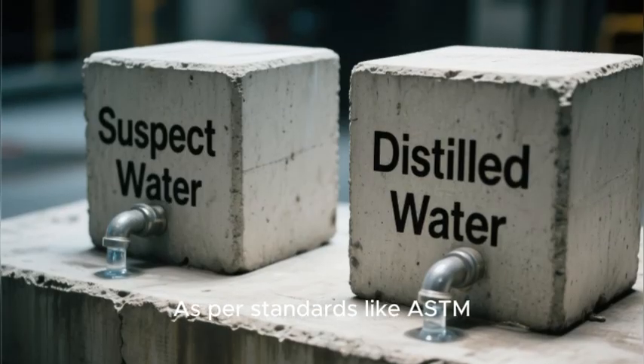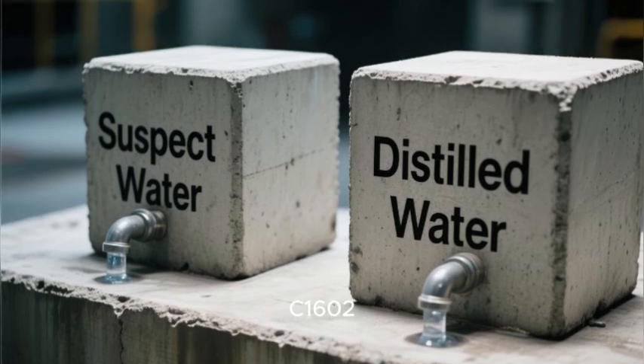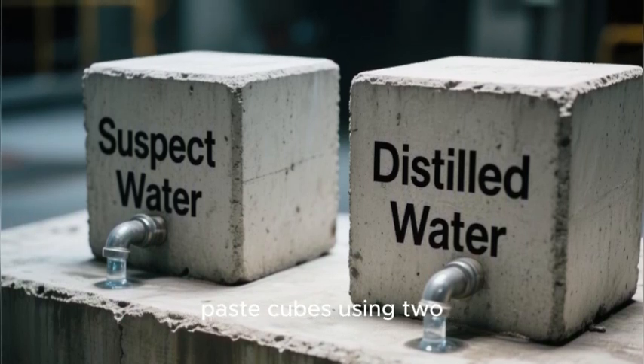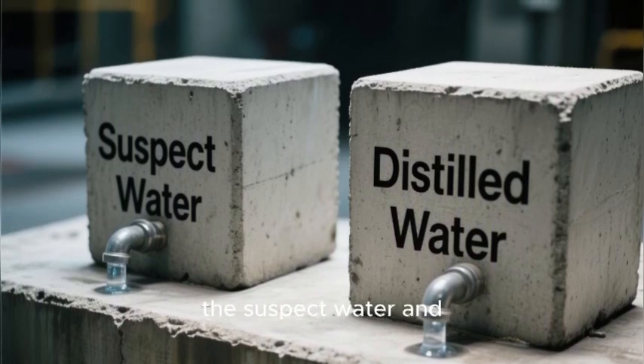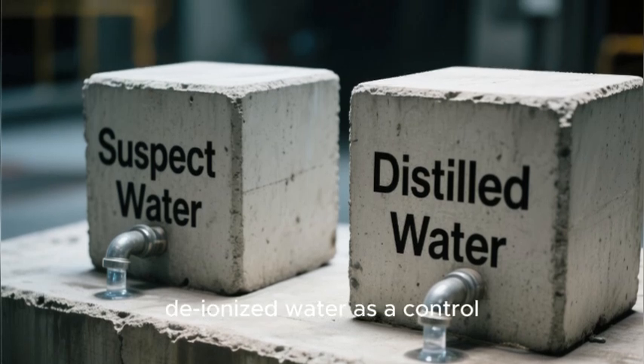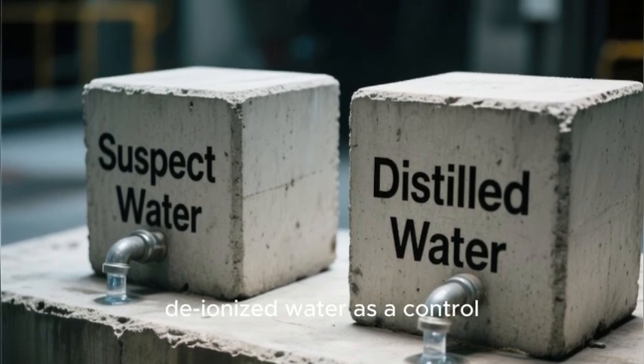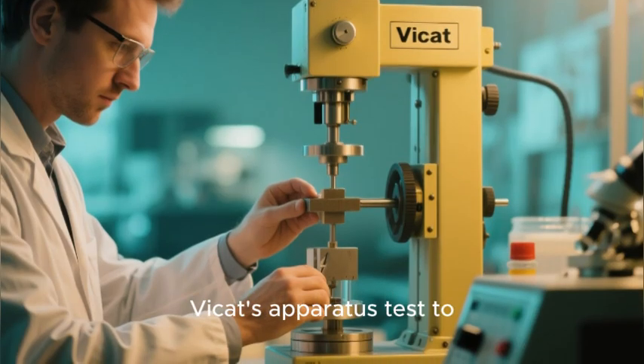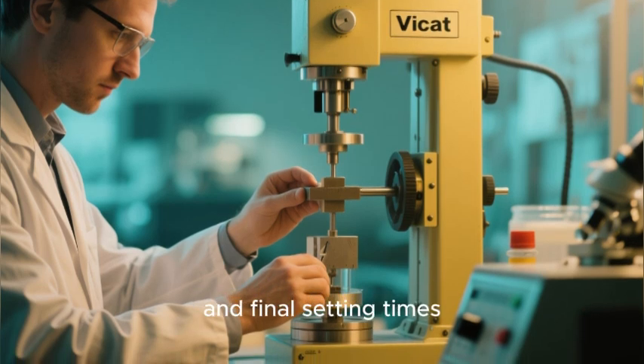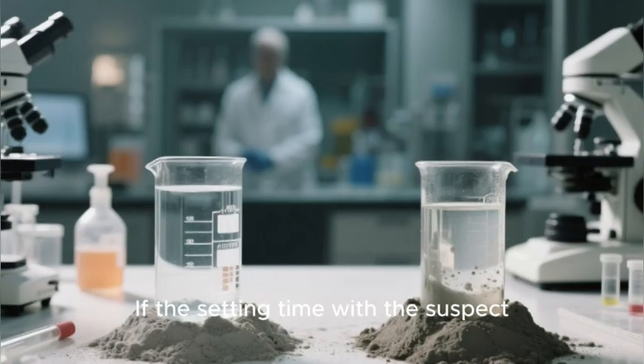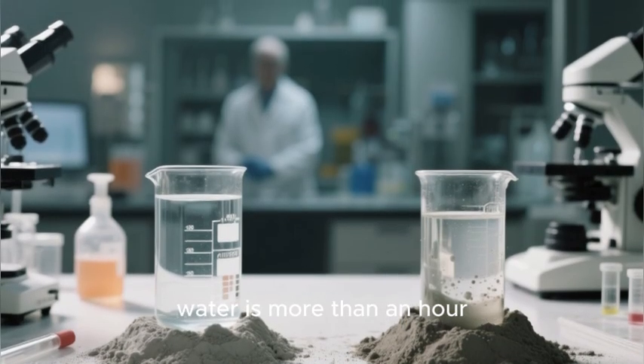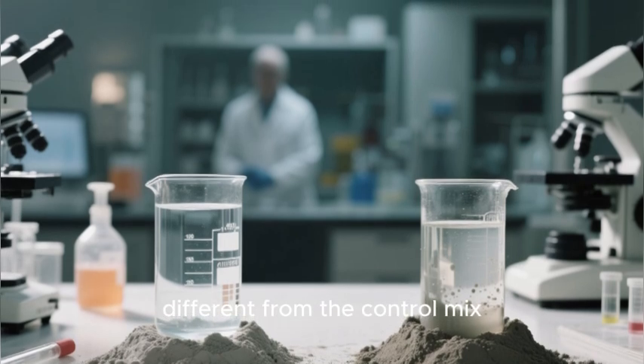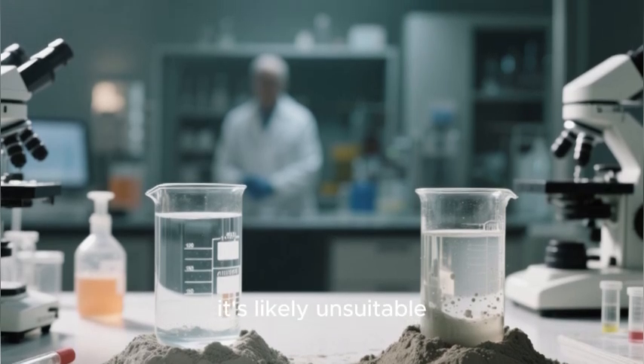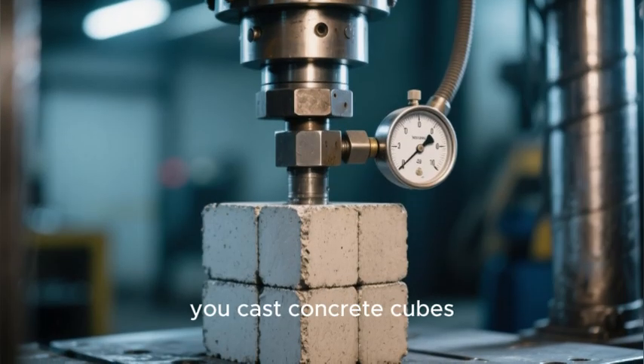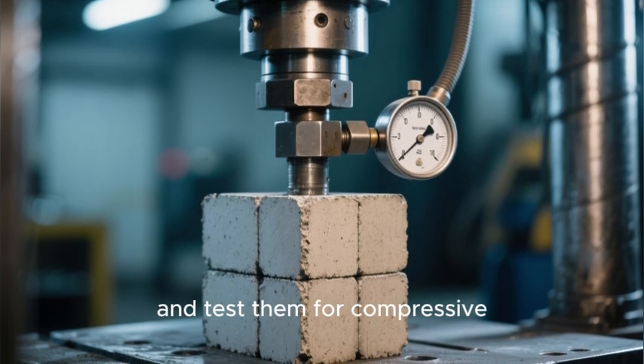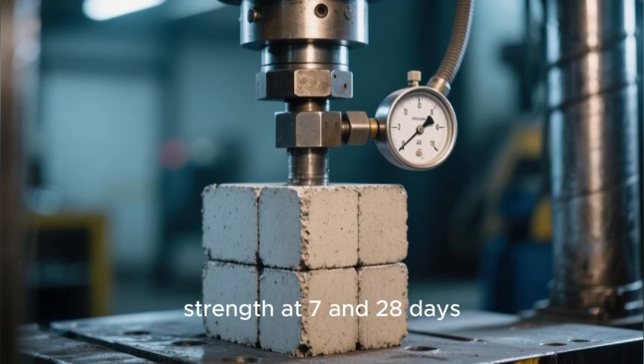As per standards like ASTM C1602, you prepare concrete or cement paste cubes using two types of water, the suspect water and distilled or deionized water as a control. You then conduct the Vicat apparatus test to determine the initial and final setting times. If the setting time with the suspect water is more than an hour different from the control mix, it's likely unsuitable. Similarly, you cast concrete cubes and test them for compressive strength at 7 and 28 days.